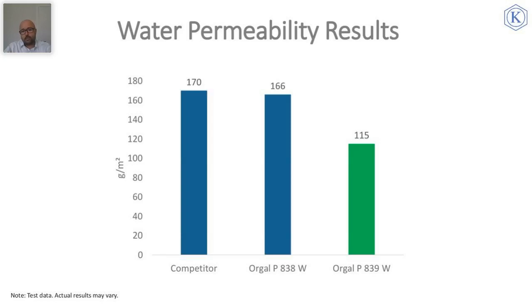But I would like to draw your attention to the improvement done by 839W. So both binders are on the level of 170 grams, 166 grams per meter square. With 839, we have remarkably improved results, which is very close to maybe the polyurethane resins. For an acrylic resin, it's a very good result. It is 115.